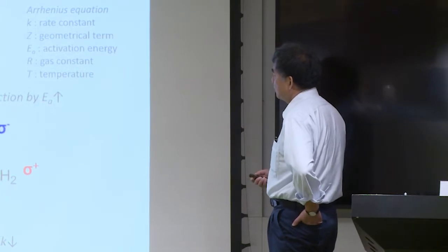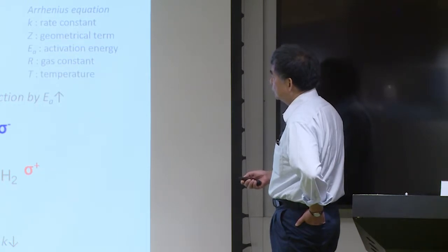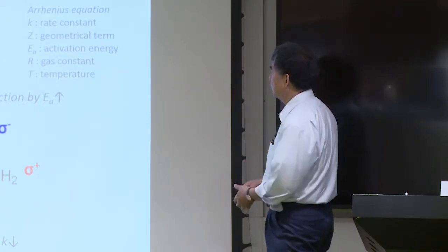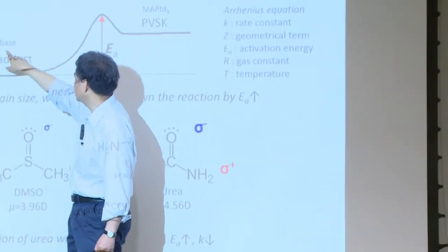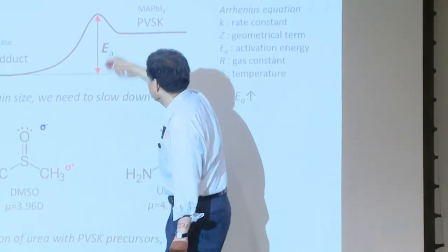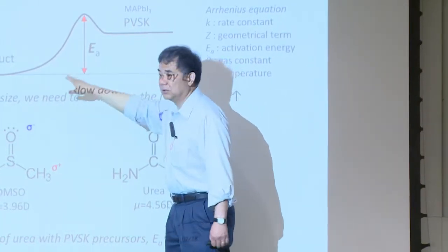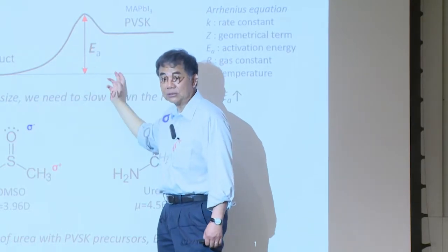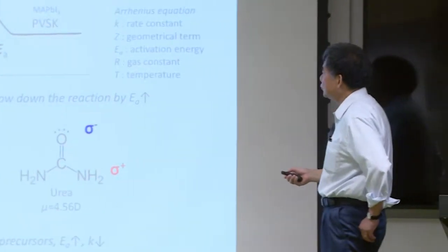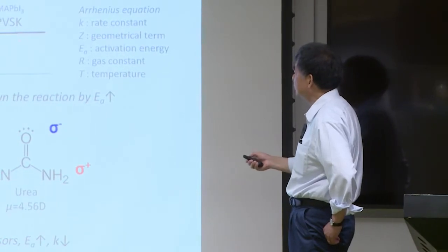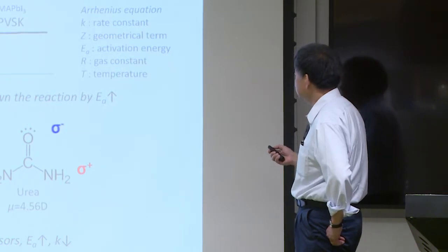What happened to the Perovskite? You do the crystal formation, you form a Perovskite crystal or polycrystalline. You put the Lewis base here, you increase the activation energy. Let's say there's no activation energy. You lower this one, so these two are interchangeable, and that's not good. You could have a phase, you switch back. So the idea is let's increase the activation energy. So it's a one-way street. You're coming over here, it never goes back. Okay, so this is the typical kinetics Arrhenius equation.